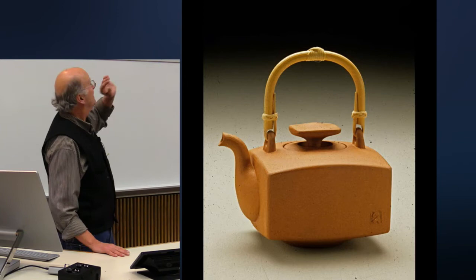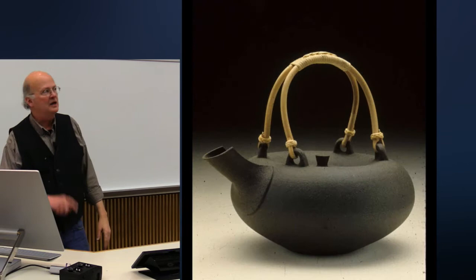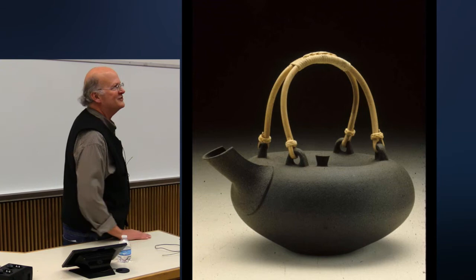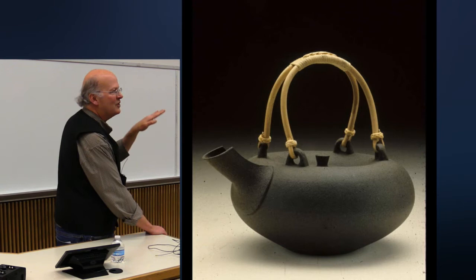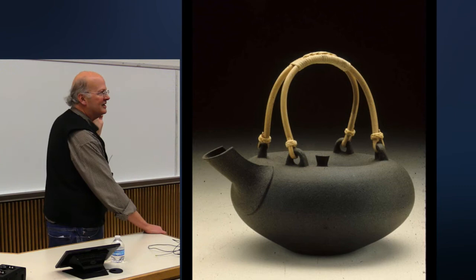So I made pots from that kind of clay and fired it using excess fuel both while the kiln was going up and while the kiln was going down. And lo and behold, that red iron oxide in the clay was turned to black iron oxide, and I had black pots.